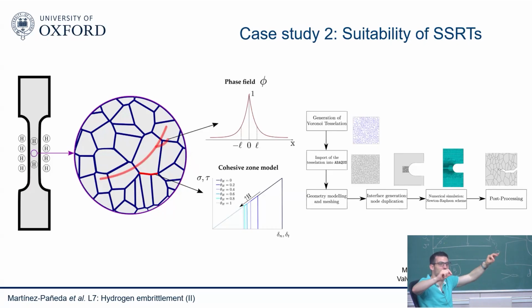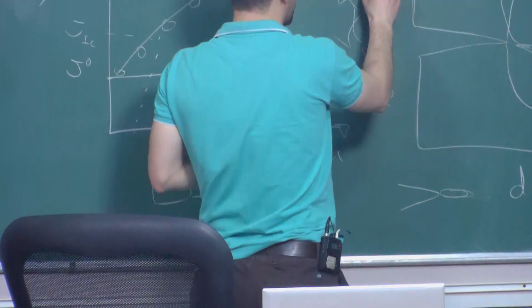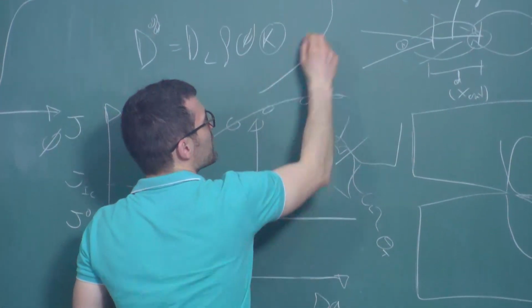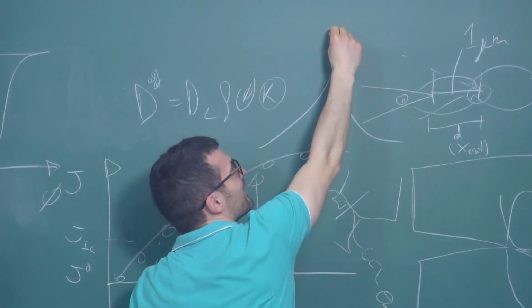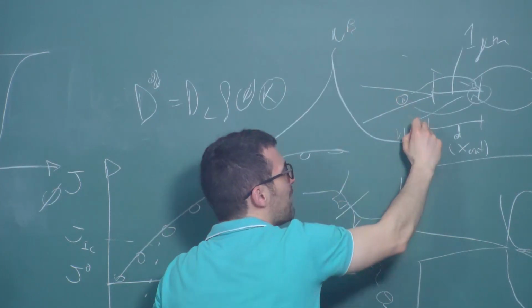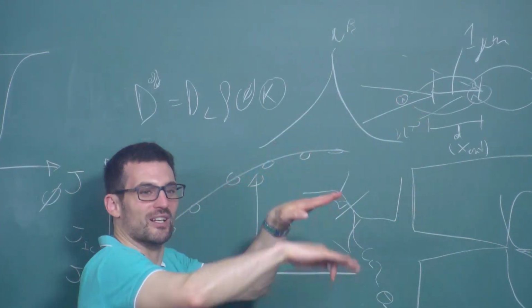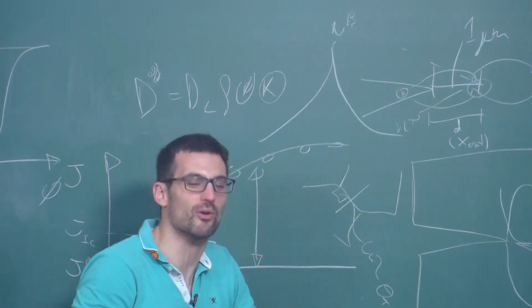So at the beginning we say we use a phase field or any other interpolation function to describe grain boundaries, and therefore we can say the binding energy changes. If I look at a graph like this, you could have a phase field that goes like this, and you can say the binding energy goes from this value to whatever bulk binding energy you have. So the change in activation energy from one to the other. This is more or less what we're doing right now.